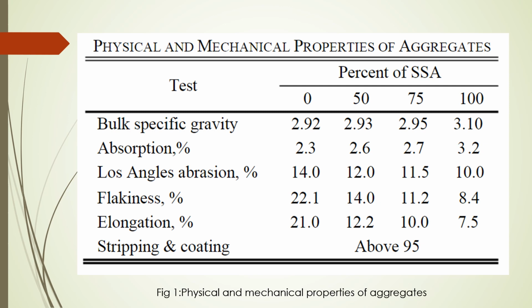These are some physical and mechanical properties of steel slag aggregate. The test conducted on bulk specific gravity. When the percentage of steel slag aggregate is zero, its value is 2.92, and when percentage of steel slag aggregate is 50%, its value is 2.93. When the percentage of steel slag aggregate is 75, its value is 2.95. When the percentage of steel slag aggregate is 100%, the value of bulk specific gravity is 3.10. We see that the bulk specific gravity increases with increment of percentage of steel slag aggregate.